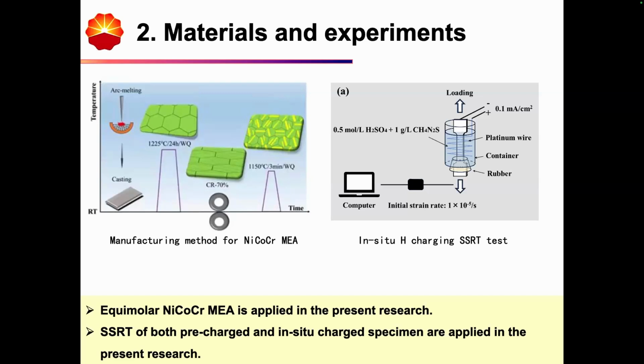For the cathodic hydrogen charging, our proposal is that the nanotwin structure doesn't suppress hydrogen enrichment. Instead, the lattice distortion suppresses the entry, diffusion, and migration of hydrogen into the material. If hydrogen has new surfaces for its diffusion and propagation route, the hydrogen resistance will sharply decrease.